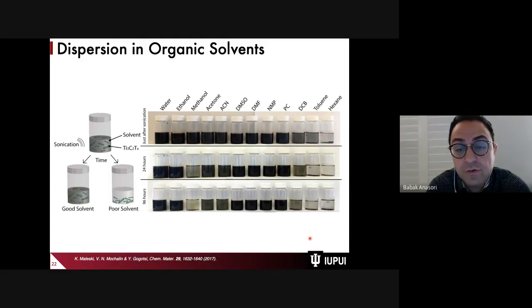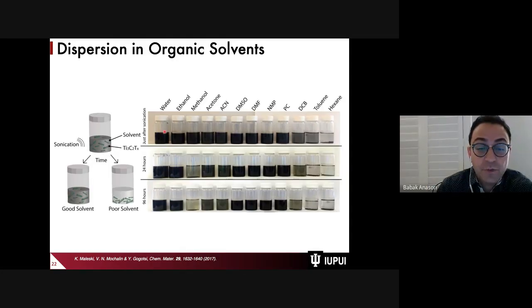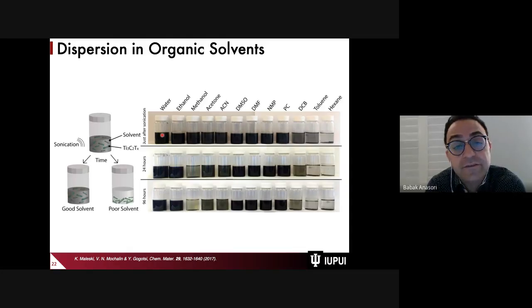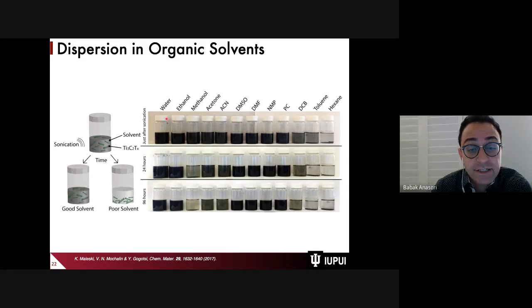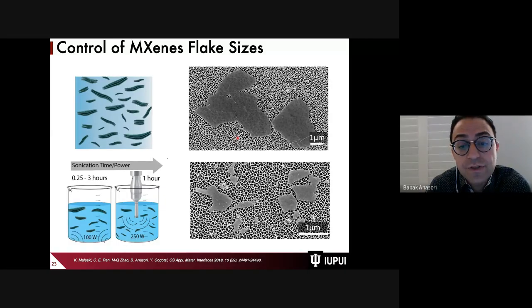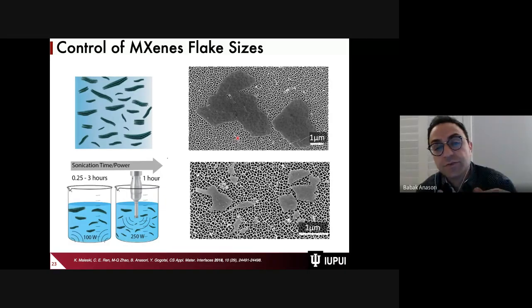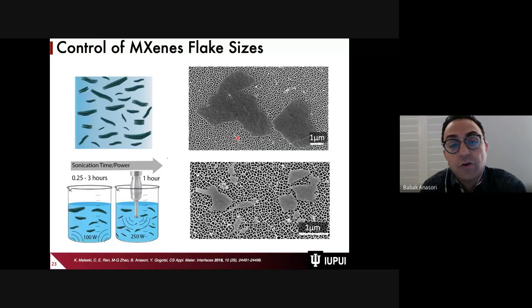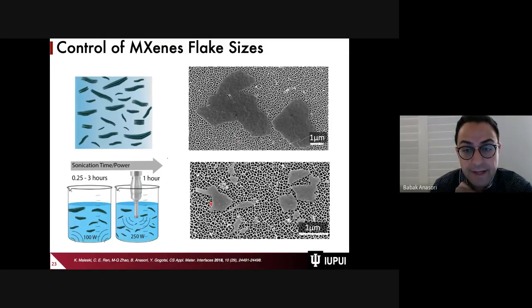And if they don't like to be dispersed in anything, more specifically, if they don't like water, meaning that they are hydrophobic, you will have a very hard time working with them, because they don't like to bond to any surfaces. But if they are hydrophilic, they can easily get dispersed in water, and also different solvents like ethanol, acetone, and other organic solvents. We can control the single flake size, meaning that we can control whether they are 5 or 10 microns, or very small, like a few hundred nanometers. And by that, we can control their properties as well.